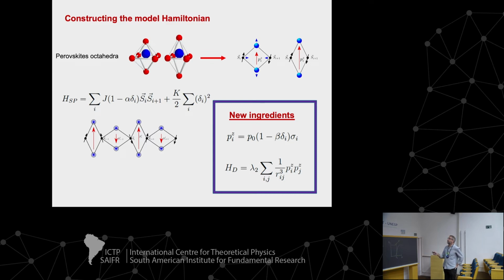So we mimic this. I will start with a 1D case where you have spins on a line, and then you have some electric polarization that could be there before the deformation or simply could appear because of the deformation. But the main idea is that when this one distorts, for example, if this gets shorter, this will get larger, and then the polarization will be bigger, okay? So this is what we call the pantograph effect. And this is how we simulate this.